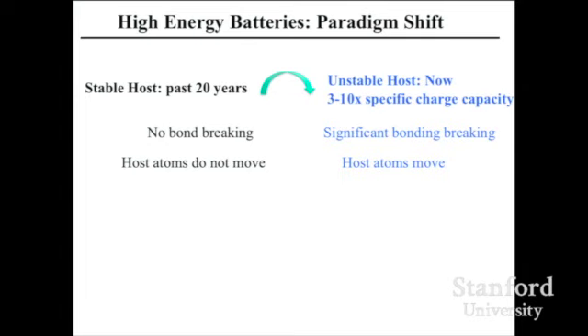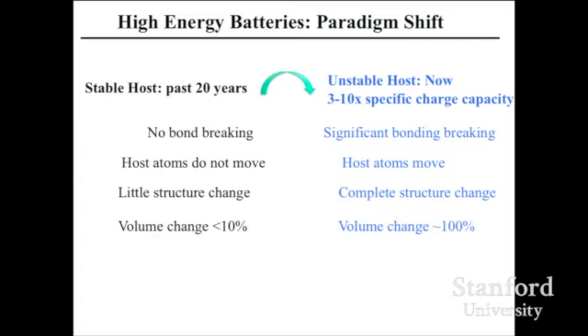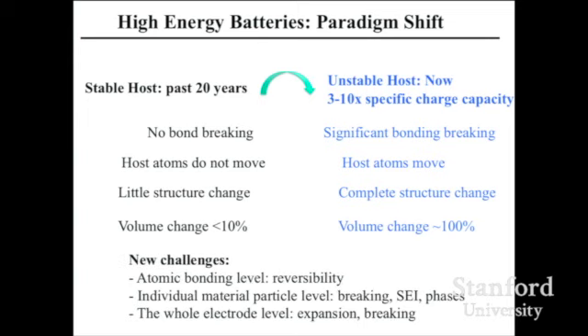So once atoms move, the structure is not stable. They can collapse. There is little structure change on the left, complete structure change on the right. Volume change is less than 10% on the left. But it's really big on the right, 100% or more. So this really presents challenges at the atomic bonding scale, the individual particle scale, as well as the whole electrode scale. How do you really make those materials work? The thinking needs to be changed.